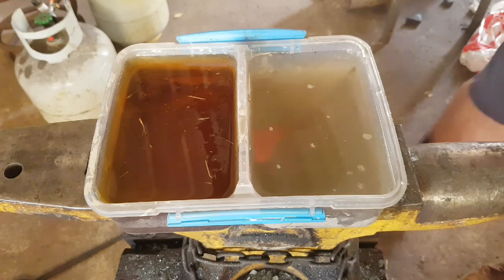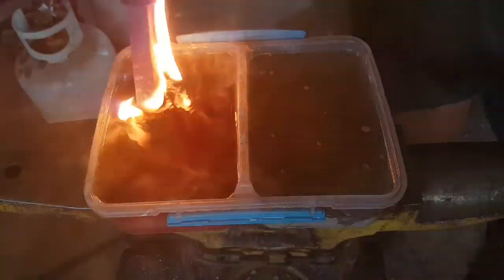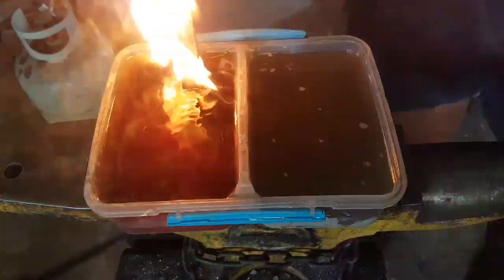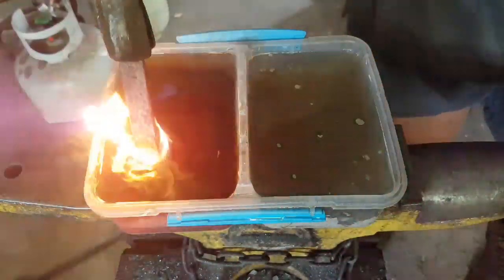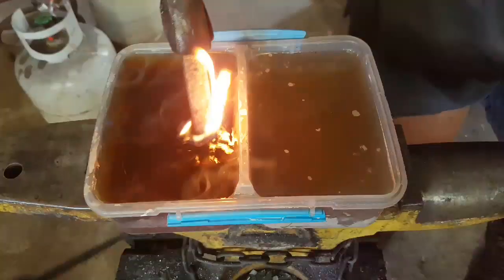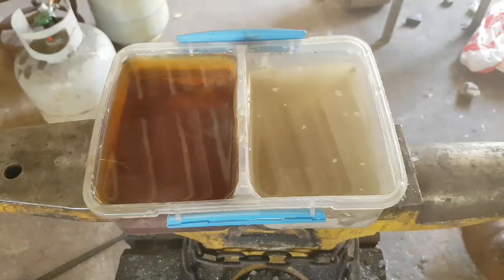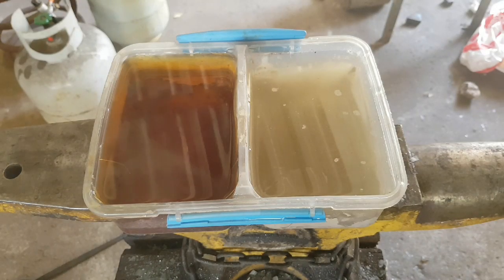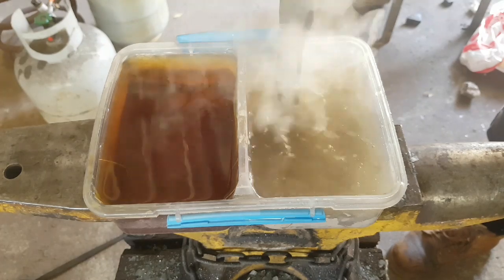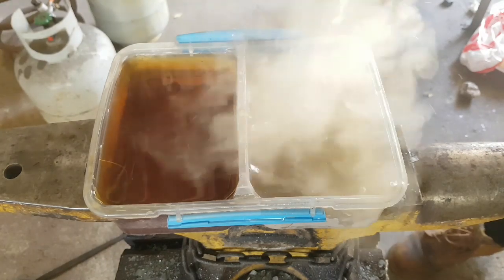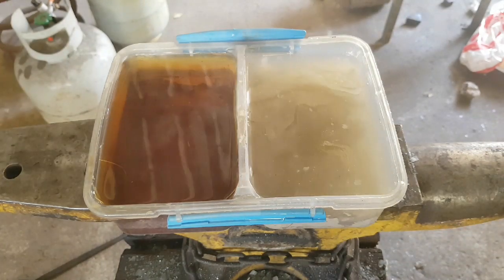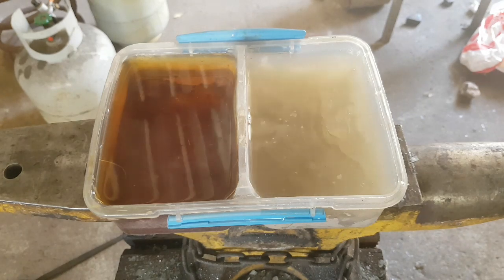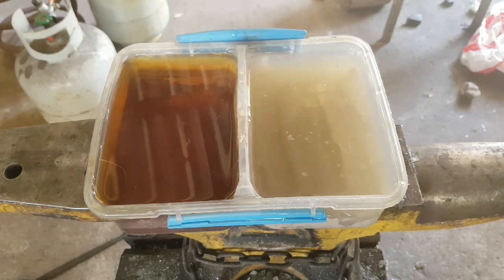As always, you preheat your oil, but in this case you're going to overheat your oil from what you would normally do because you're wanting this oil to prevent overcooling from the water and prevent cracking. I also preheat my water. Warm water will less likely crack a blade than cold, though you don't want it close to boiling or anything like that because that'll create too much of a steam jacket and you won't harden at all.